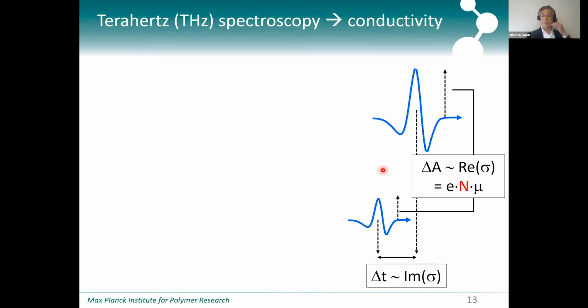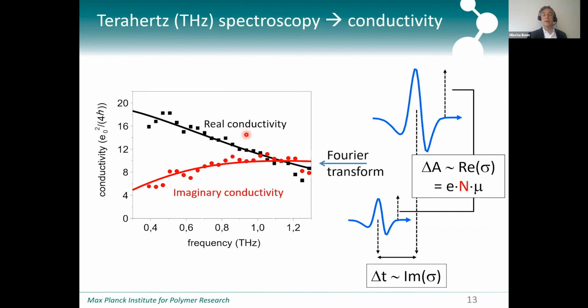And so we can analyze that in a little more detail by taking the ratio of those, or the difference of those two, actually the normalized difference, and Fourier transforming it. And so then we can really determine the real conductivity and the imaginary conductivity as a function of frequency. So it's clear that if you have such a single cycle pulse, it is a very wide pulse, so to speak. It has to contain a lot of frequency components. And indeed, the bandwidth of this pulse is about a terahertz, and it's very similar to its central frequency, which is also about a terahertz.